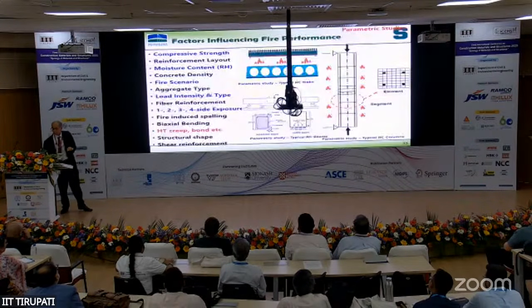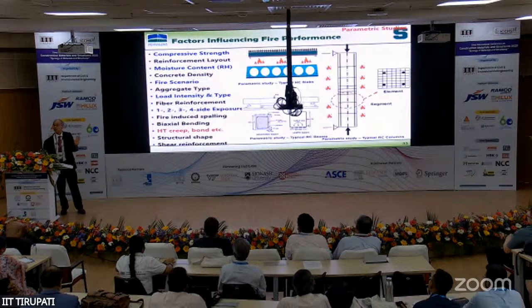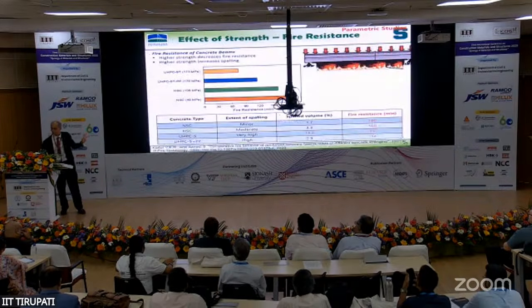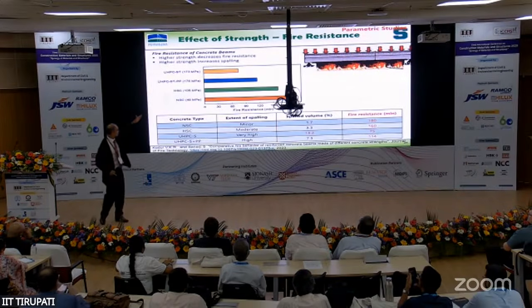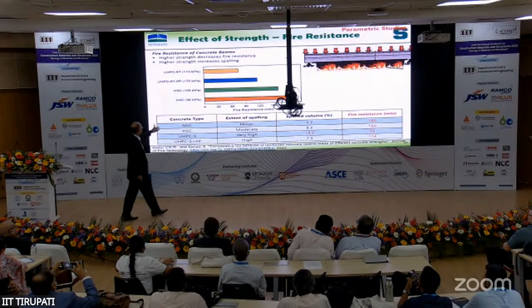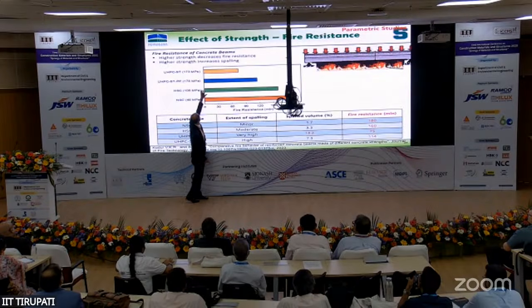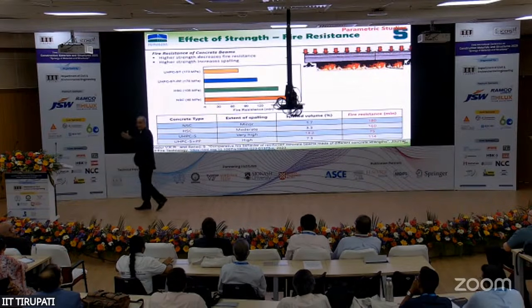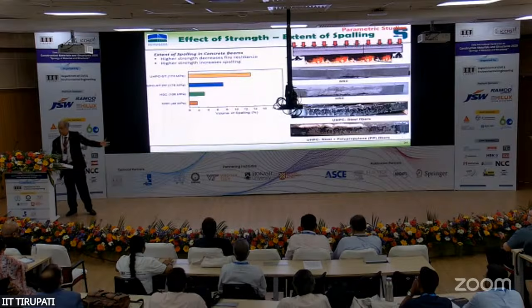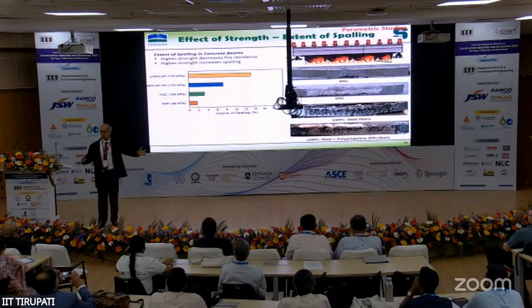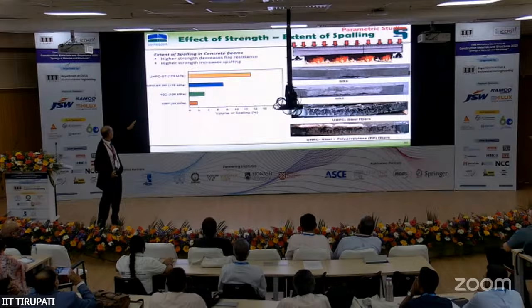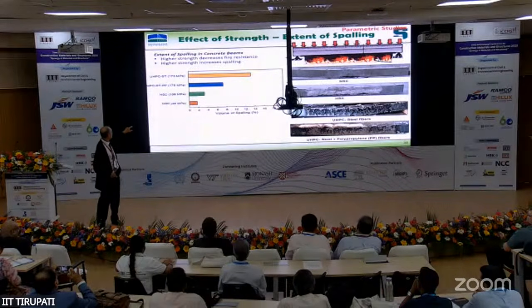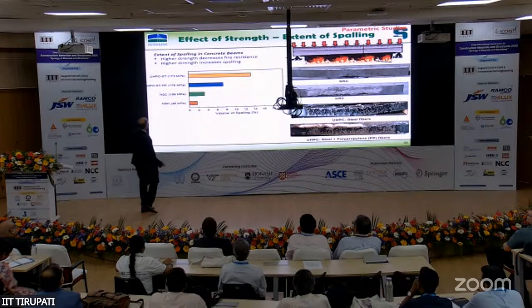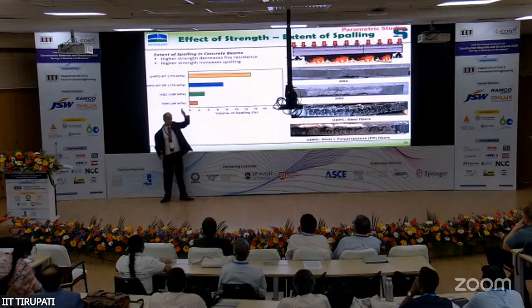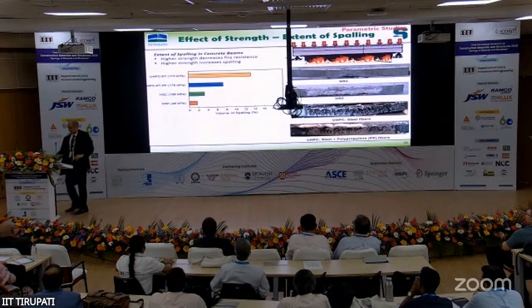Okay, so basically, then we varied a lot of factors, which is very important. It's not just the cover thickness and the size as the codes say. So you can quickly glance through this. Basically, I already explained to you, conventional concrete 48 megapascals, high strength concrete, okay, how long it takes for it to fail, right? And how much spalling happens. If you add polypropylene fibers, you can reduce, increase, normal strength concrete beam, it's opposite. Yeah, very less spalling, more, right? So the extent of spalling.